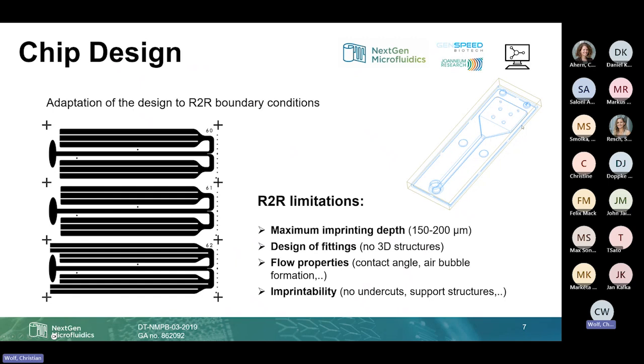And when you look at the ChipShop chip here, the waste compartment has a depth of 600 micrometers. That's not doable by roll-to-roll imprinting, because you still need a substrate foil and a cover foil, so that easily sums up to a thickness of the full chip of 900 micrometers to 1 millimeter, and that would be no lab on a foil anymore, it's then probably more lab on a plate or something like that, where you also already get problems with unwinding and so on. So that's one limitation you have to consider in your design, and that's why the roll-to-roll chips also have those big waste channels, waste compartments, because they are needed to take up all the liquids which are used in the testing protocols on the chip.